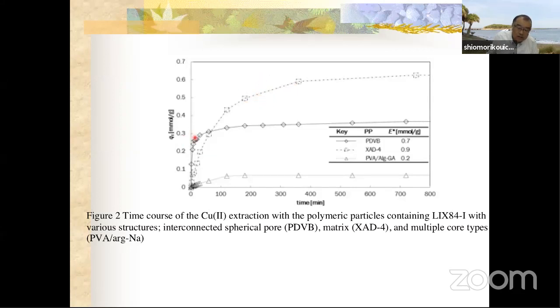On the other hand, the interconnected spherical pore type capsule particle can give a high surface area between the extractant phase and the aqueous phase. So it gives a high extraction rate like this, but the surface is saturated by the extraction complex, so the extraction rate goes down a little bit. Like this, it reaches a constant value.